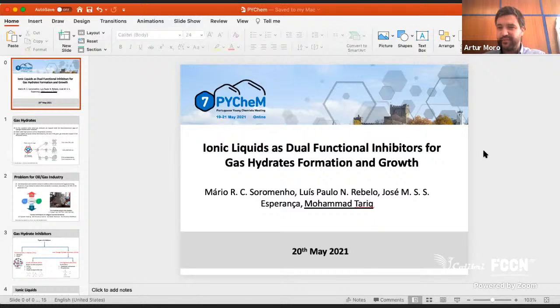And in these conditions, right? Yes. And then you have different temperature conditions, different pressure conditions. The driving force for hydrate formation is the initial pressure and the subcooling, how far below the equilibrium you are going, where the hydrate can exist. And in big systems, it's very difficult to maintain. There are people who have an instrument, even without any inhibitor, and it's very difficult to predict, even for CO2, when the nucleation is occurring. So nucleation occurs somewhat before, but what you are seeing is the induction time.